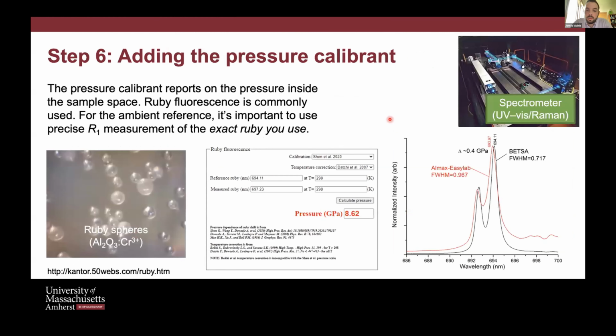The pressure calibrant, this is important. I'll make one or two comments because it's already been touched on by Fraser and Stas, but the standard usually is to use optical calibration. You can also use X-ray calibration. You can look at the unit cell of something that's been calibrated to get to pressure, but often it's more convenient to use an optical method, and for that, ruby spheres are pretty common. I think most groups will use this unless there's a reason to use something else.